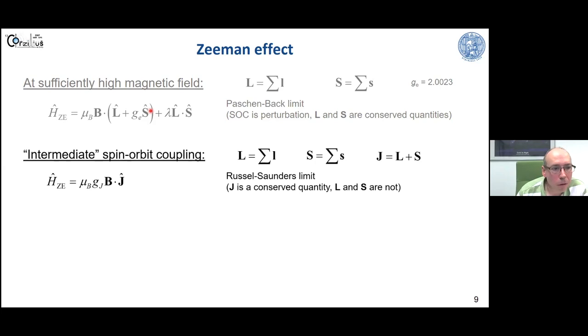It becomes more complicated if we cannot separately treat orbital and spin momentum and just treat the spin orbit coupling as a perturbation. If we go to the intermediate spin orbit coupling, that means spin orbit coupling is on the same order as the interaction of orbital and spin angular momentum with the external magnetic field in each case, respectively. In this case, we can still create a total orbital momentum of all the electrons in our system and the total spin momentum of all the spins in our system. And then this combines to a total angular momentum, J.